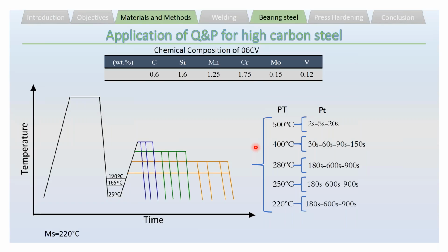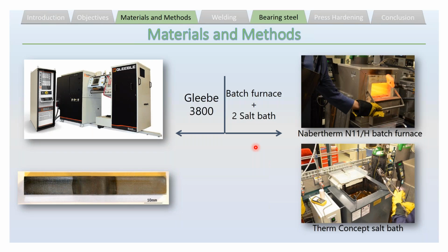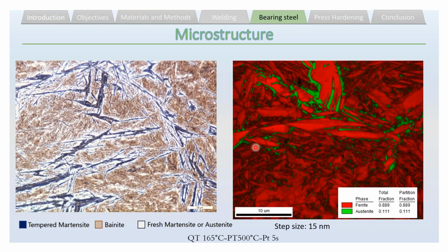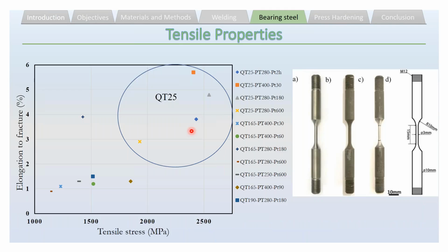The second application is about bearing steel. We also used quite a high carbon steel, 0.6 C with 1.6% silicon, and tested different conditions. We used both Gleeble and furnace plus 2 salt baths to prepare the samples and compare the results. Here you can see the microstructure. I think this picture could show you the austenite around the martensite, which is stabilized during partitioning very well. And it's the same in the color etching by optical microscopy, where you can see austenite in white and tempered martensite in blue.